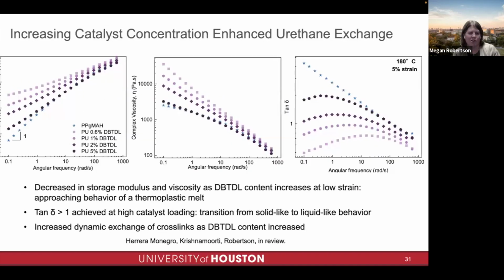And I'll note, we actually looked at rheology to see that exchange process. Here we were looking at the storage modulus. If our polymer were a linear polymer, this slope would be 1, like a linear viscoelastic material such as the maleic anhydride functionalized polymer we started with. When we make the polyurethanes, you can see this slope increases. So at the lower catalyst loading, it's not flowing exactly like a polymer melt would if it were a linear polymer. But as we add more and more catalyst, it reaches that limit.